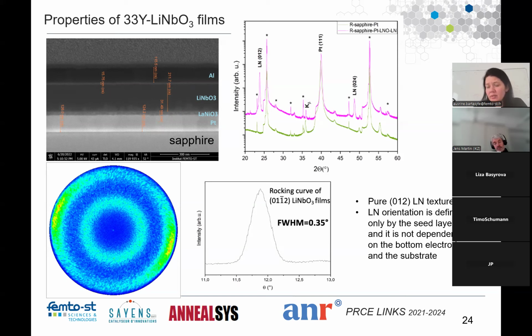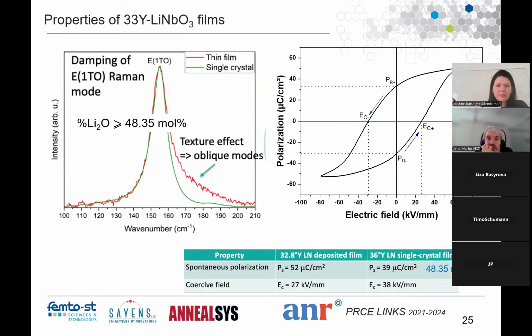Platinum is epitaxial. It's 111, but it's epitaxial. The lanthanum nickelate normally is not oriented in the plane as well, so it's sort of textured, but it has these two preferred orientations. As we see here in this pole figure, there is some preference in lithium niobate in these two orientations. So it's a textured film, it means like fiber texture, okay? There is no in-plane orientation, but there is some preference in two orientations.